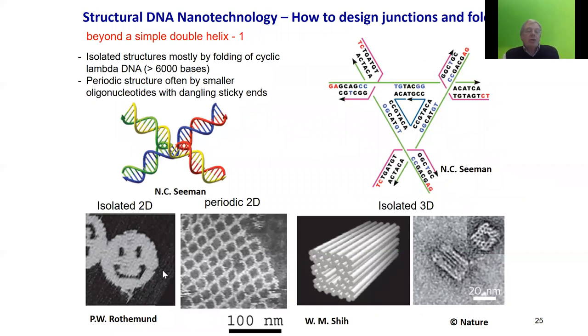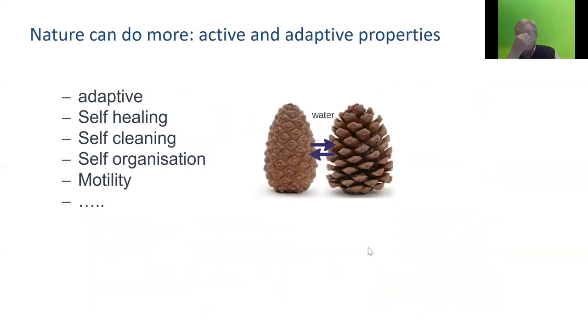And that this was possible is shown in here by the electron micrographs from Rothemund in here. Other things are possible, like the periodic 2D lattice in there, or mesh in here, or three-dimensional structures like shown in here. So all these things have been done. And nowadays we can do it, or people can do it even in the gram scale already and not only on the microgram. So we have this further development going back towards aggregation, association, reversible bonds, and to use these to control the buildup in what I call the hierarchical structure.